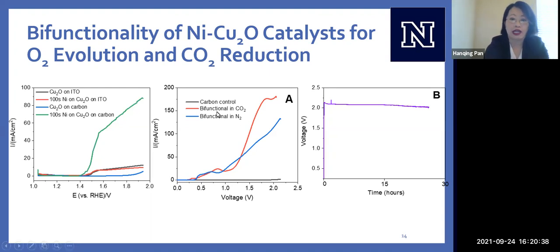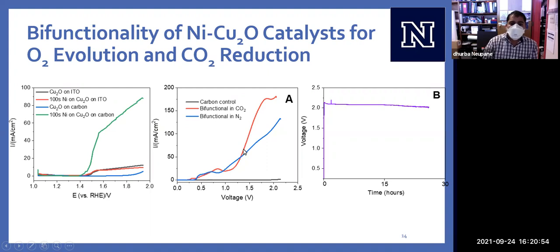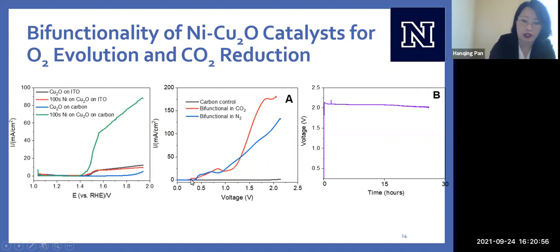We can also look at this reaction now bifunctionally. We can study this under CO2 and nitrogen just to confirm that CO2 reduction is happening. We can test a control, so what is carbon alone doing? And we're looking at this red line. This red line has the earliest onset potential and the most current density. And so our catalyst is the best in CO2 compared to all the controls.